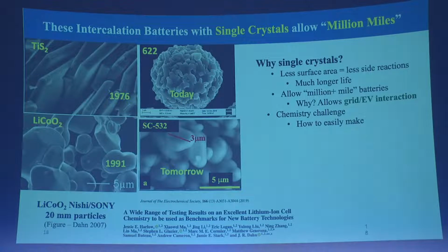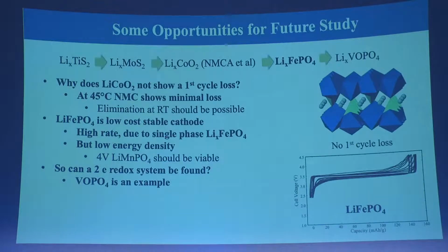And my colleagues at Pacific Northwest National Lab have done more in-depth studies of single crystals, and they say you want single crystals between about 2 microns and 4 microns in size. They pack best, and above that size they will crack, below that size they will not. So they're optimizing that. Just let me switch to a few other compounds for the last few minutes.